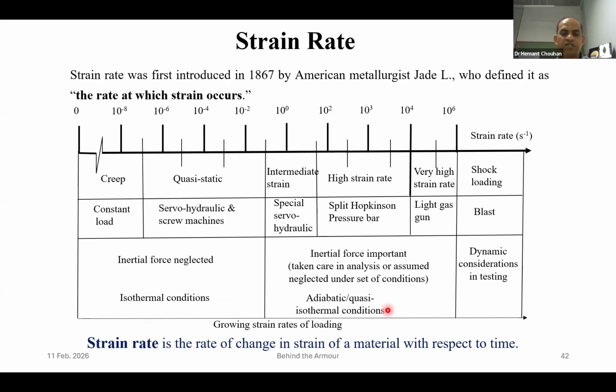given by the UTM machine or not? For that, we should understand what is the rate of loading or strain rate. So it is this low. I won't go much into this for time reasons. This is the location wherein we have quasi-static testing, which we call UTM, where inertial force, that is the effect of mass, can be neglected and time is sufficient that the event can be considered isothermal. But the bullet is somewhere over very high strain rate of loading.